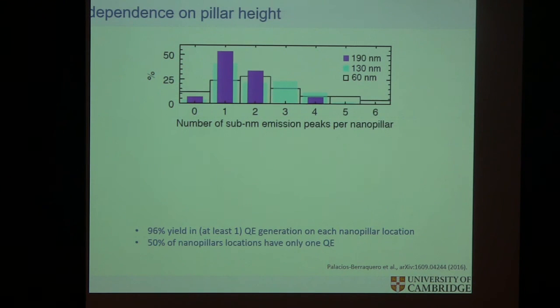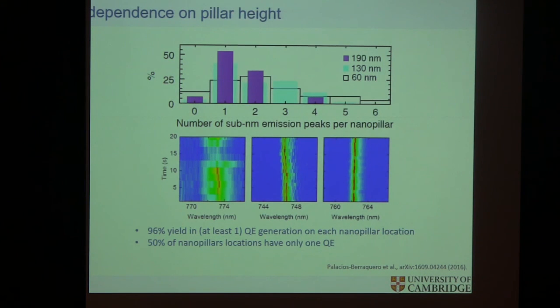And here what you're seeing is 2 very interesting features I would not have expected. One is you have 95% of all the emitters exactly where you want them to be, and it's only one emitter. So it's not that we have multiple emitters formed, but they're deterministic one at a time, 50% of the time. There's a joke with Anchorman movie: 50% of the time it's deterministic. It's exactly that. 5% of the time is nothing, 50% of the time is only one, and then it varies.